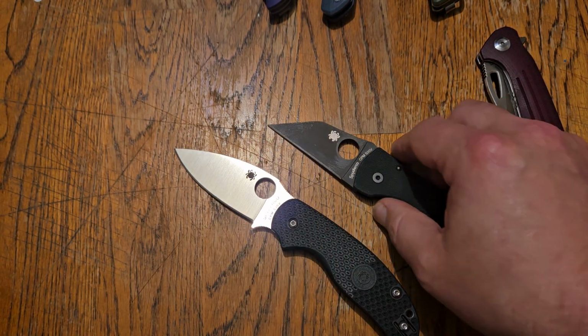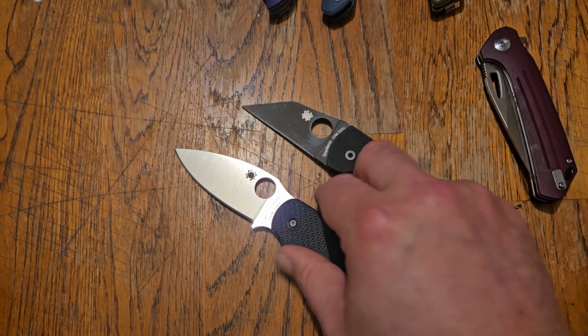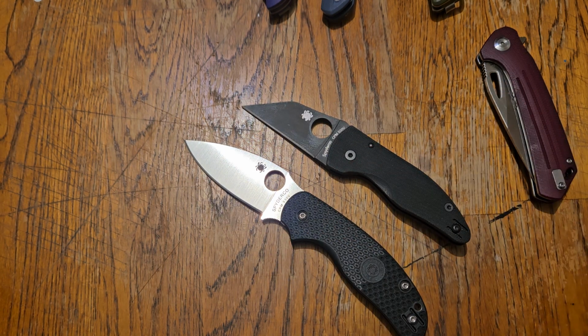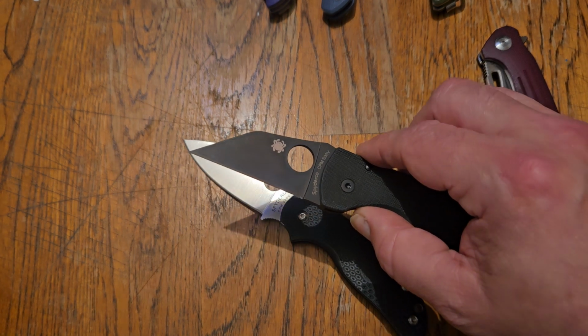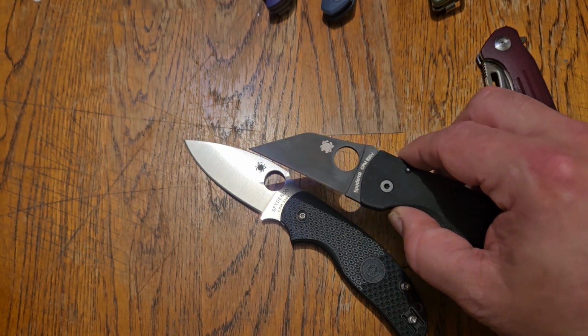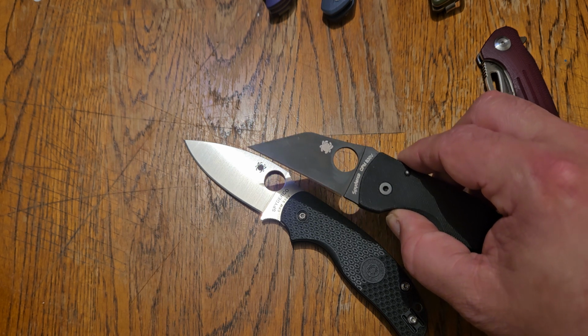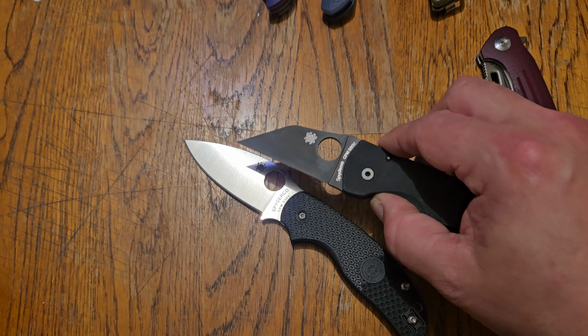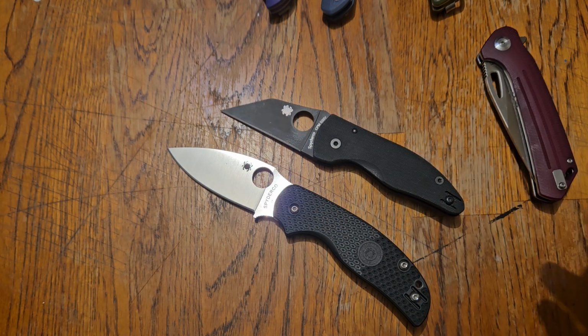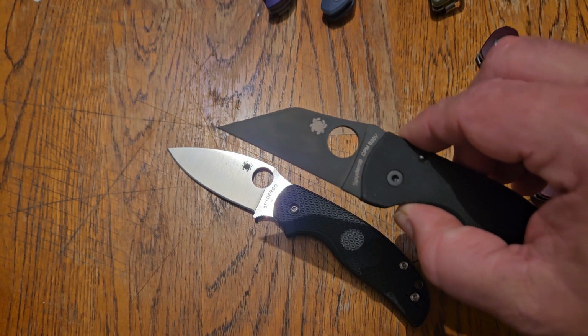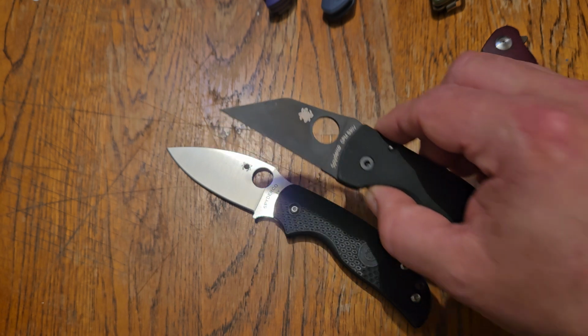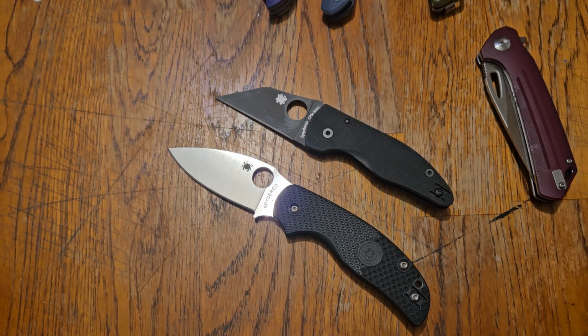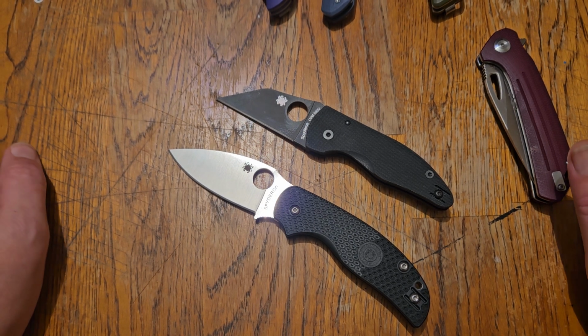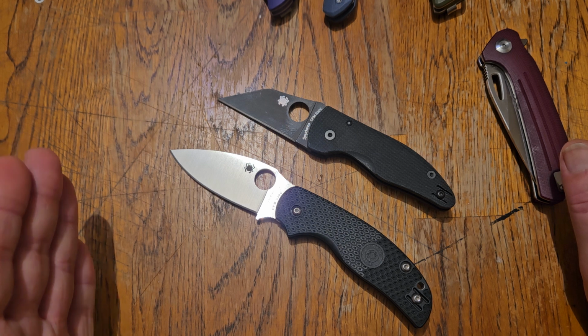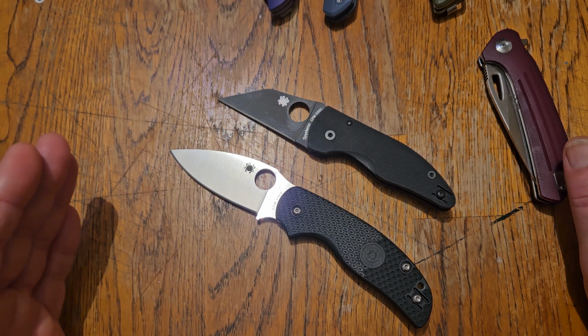If the geometry is the same, both pieces of S30V, and this is 61.5 Rockwell, and this is 60 Rockwell, guess what? Even if the heat treat was better, if this one just happened to be in a better place in the oven and has a dead perfect heat treat on it, but after temper it's at 60.5, and this one's heat treat is not so perfect, but after temper it's at 61.5, this one's still going to be the one that cuts the longest, because it's a factor of hardness and steel composition.